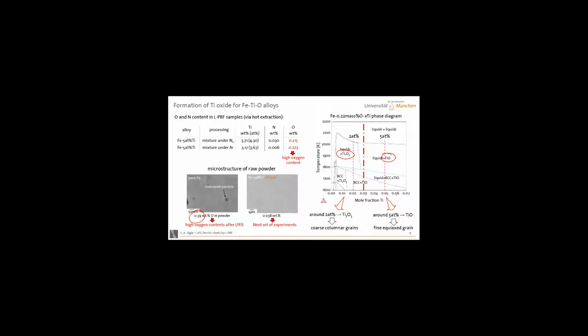One more point. Look at the nitrogen content. The 2 lines in this table are the iron and titanium powder mixture processed under nitrogen atmosphere and under argon atmosphere, and you do see a nitrogen uptake. Compared to the oxygen, however, it's practically negligible. There is a clear difference between argon and nitrogen processing, but it is not a huge difference.